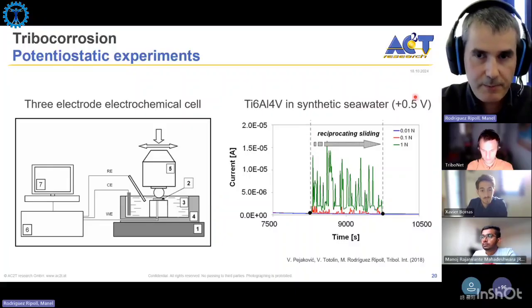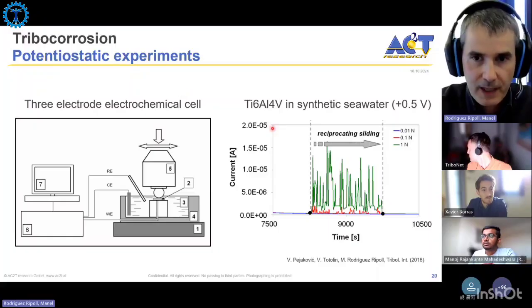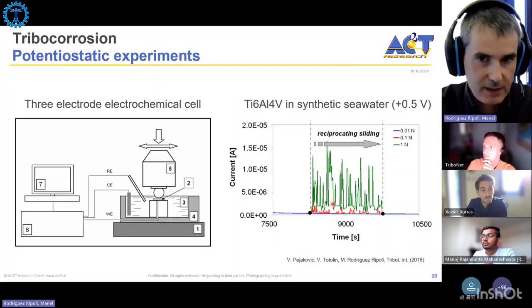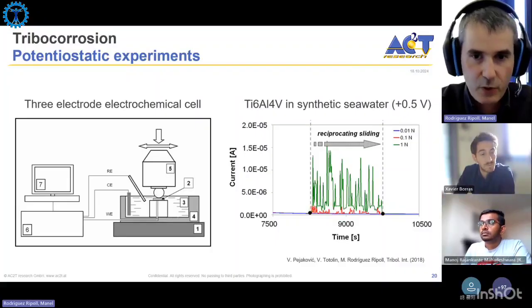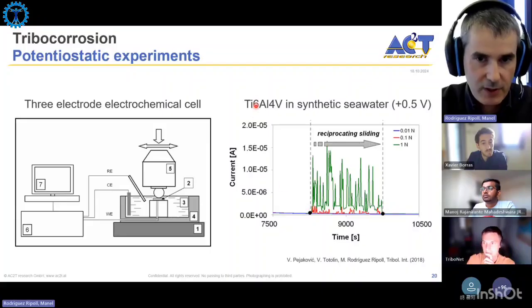The only difference is that the potential here is constantly applied. That's what is called a potentiostatic experiment, so with a constant applied potential. And we can have similar observations. So with 10 millinewtons, basically nothing happens. If we have 100 millinewtons, we can see a little current occurring in the wear track due to the currents generated by depassivating the wear track and exposing the naked titanium to the environment, and then having this active dissolution of titanium. And if we have a higher load, then the current will be larger.